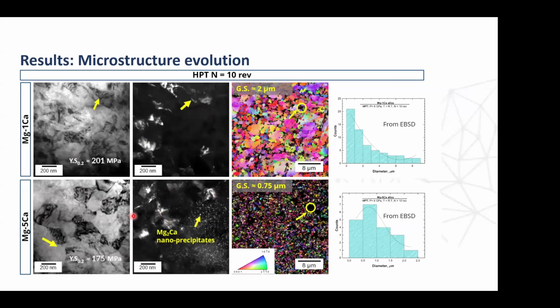What we did see is that in the case of magnesium calcium, we had a more heterogeneous microstructure, where some areas were a little bit coarser in grains than others. So we did find some areas where the average grain size could be 2 microns, but if we go to some regions, then the grain size can be significantly reduced. As you can see, for example, from the bright field and dark field images here, grains can be as small as 200 nanometers or 100 nanometers. And we also saw dispersion of these precipitates, or dispersed particles of magnesium two calcium.